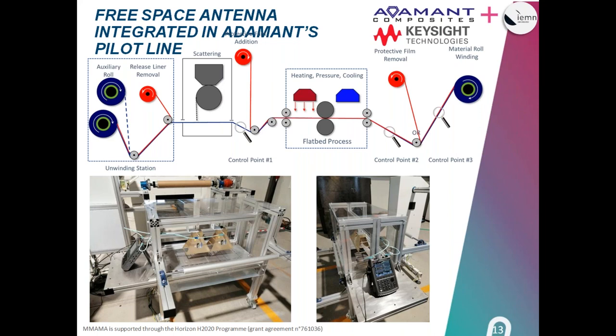So going to the main issue of the presentation, which is the integration of the free space antenna system developed by IEMN in our roll-to-roll process. I will give you a short overview of the process that we do in Adamant Composites to add specific properties to the prepregs. So we have a roll-to-roll process. Starting from the left, we have the unwinding station where we have the mother material, the reference prepreg roll. It goes through the scattering step where we introduce the dopants in the form of a master batch powder.